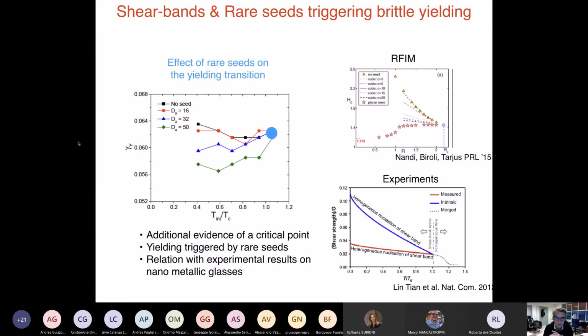And so this is the figure on the left. Here you have the value: when I deform the system, gamma y is the value at which you have the discontinuous failure of the system. The black curve corresponds to no seed. Then if I put a seed, an ellipse with a diameter of 16, you have almost no change, which means, like in the random field Ising model, that given the system size we are considering, seeds of size 16 are typically inside the system. But if we put a larger seed of 32, then the system fails earlier; the value of gamma y is smaller. And if you put an even bigger seed of size 50, the system fails even earlier. So this is very similar to what we found in the random field Ising model.